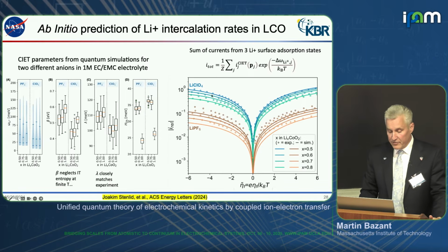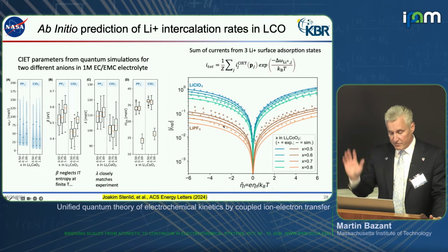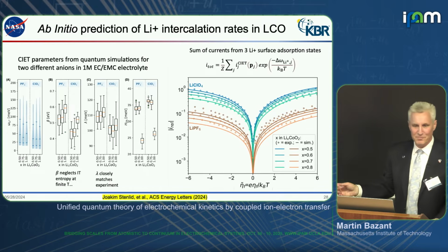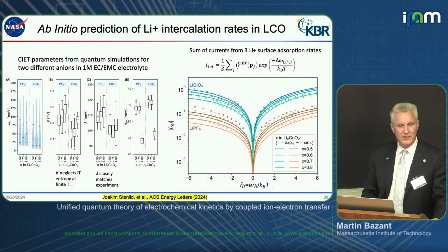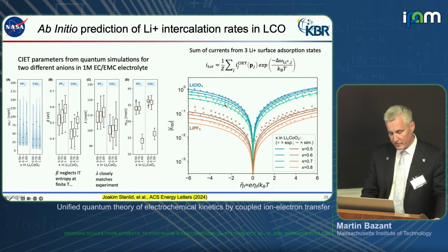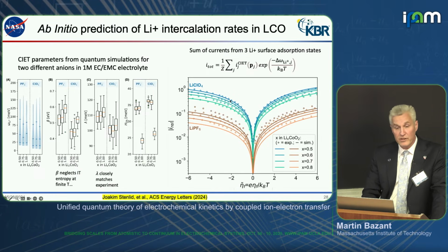Bottom line is that here they actually took the experimental data from that Science paper. And by the way, you can see how long it took us to fight with the reviewers for Science, because this was published in 2024, more than a year before the Science paper was actually published. But we had the data provided for this paper. And all that was done here is to fit one parameter. So this is really an ab initio prediction of a reaction rate from quantum first principles.